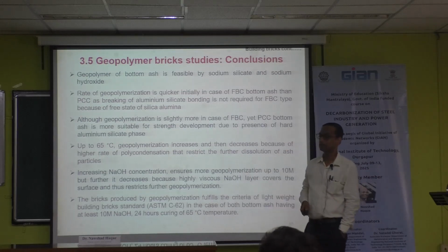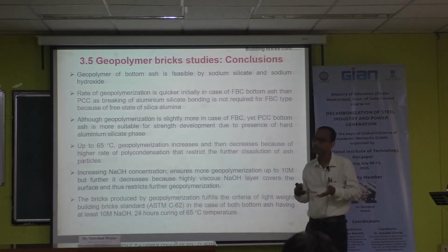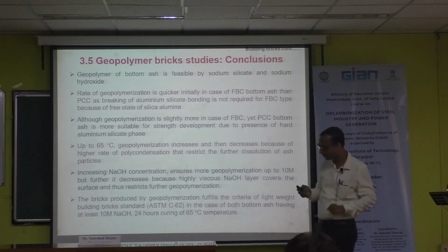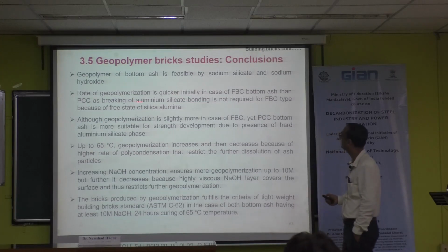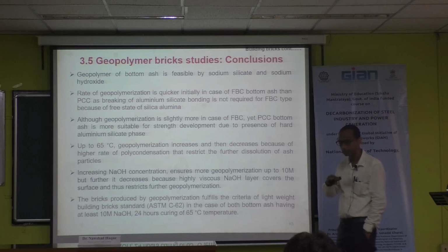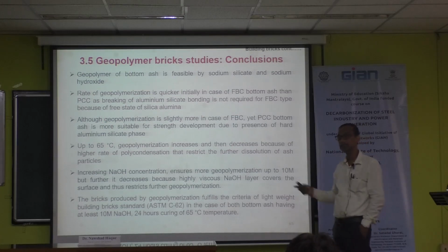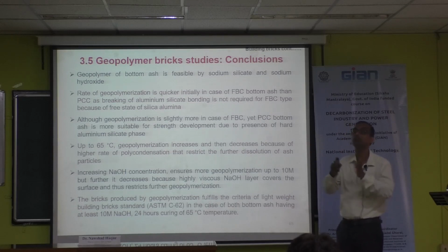But in case of PCC particles, it requires some time for dissolution. Therefore, initially, if you see, the FBC bottom ash will give you more strength, as geopolymerization is faster. But ultimately, if you see, we have shown that PCC bottom ash shows more geopolymer.